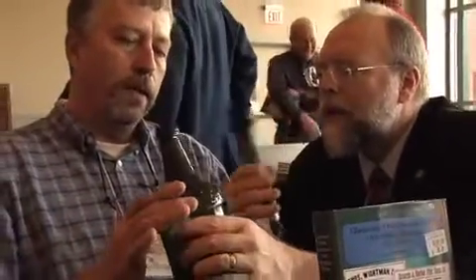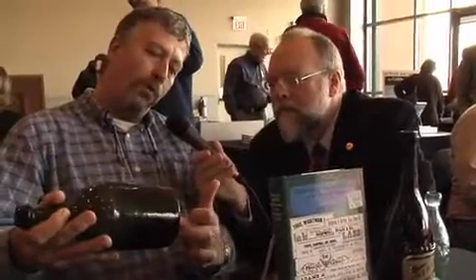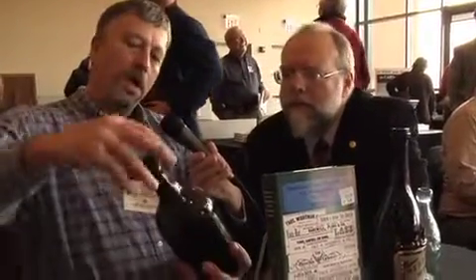How was this bottle made? This bottle was blown in a mold, and when the blowpipe was still attached, a young boy would come along and stick a rod with hot glass on the bottom, funnel it. They would remove the blowpipe, and then another boy would come along. They'd lay some glass on here, and then they would tool it to get it smooth. And then they'd snap it off, and one of those boys would take it over to be annealed.